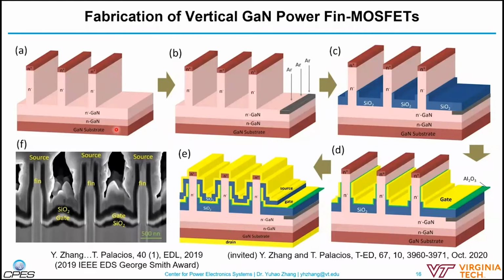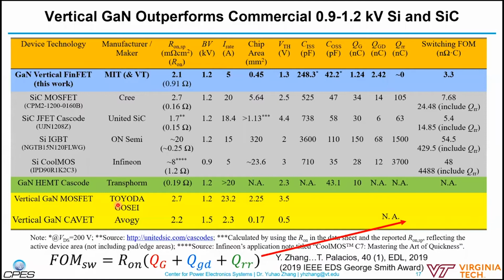So it's just starting from this fin, and then we stack one layer after the other: the first the dielectric, and the gate dielectric, gate metal, and some spacer, and the top source. And here are the scanning electron microscopy images, photos of our structure. Okay, so this is a benchmark of our demonstrated large array devices, 1.2 kV and 5 amps.